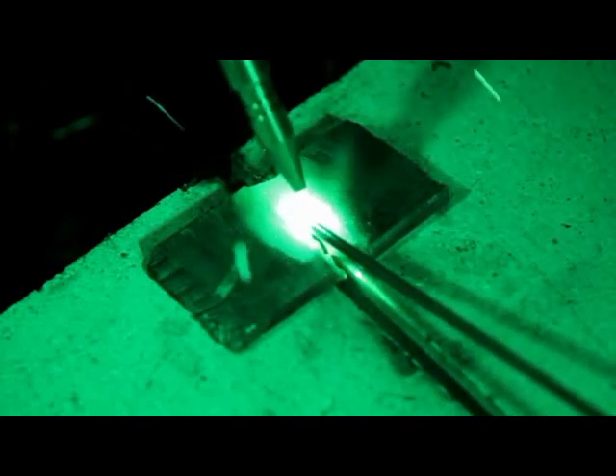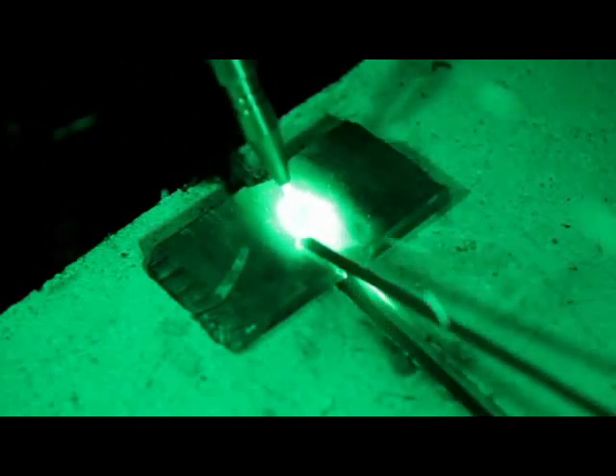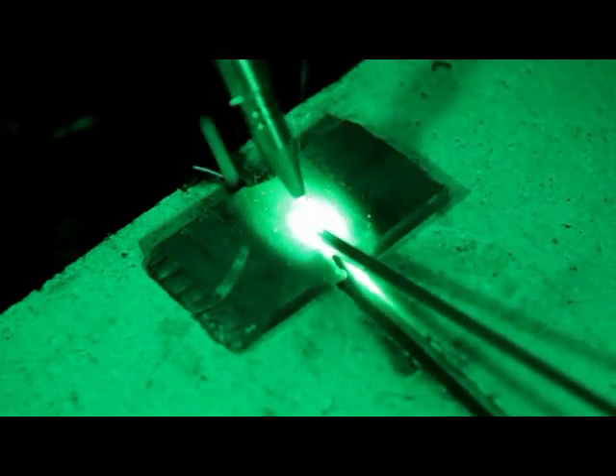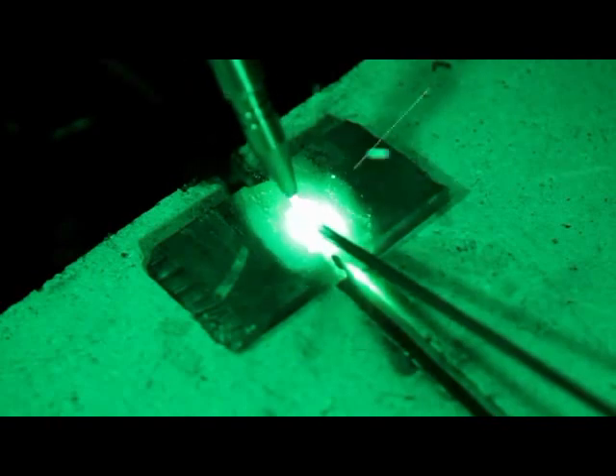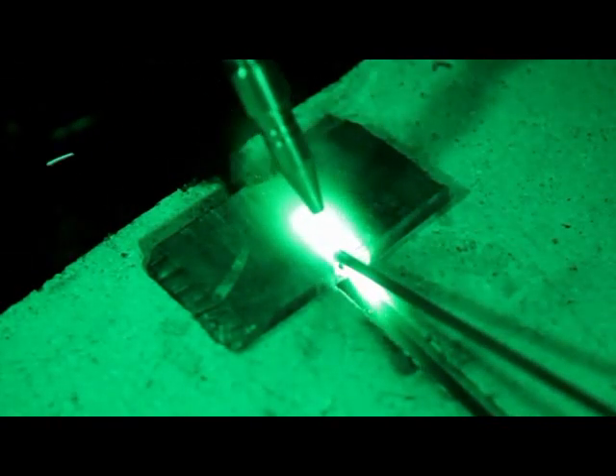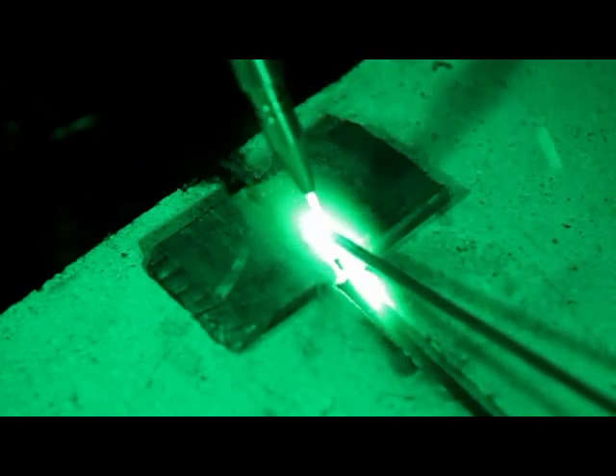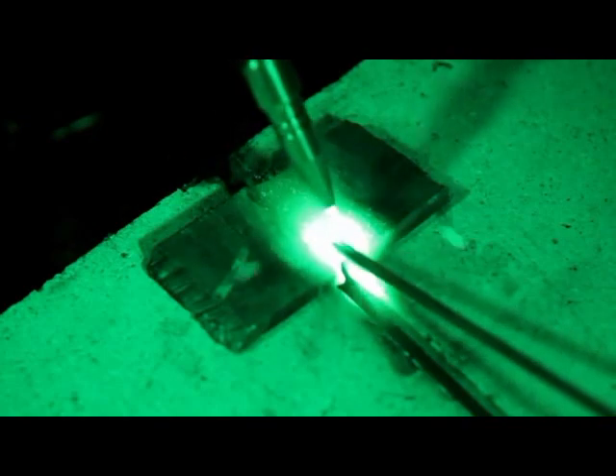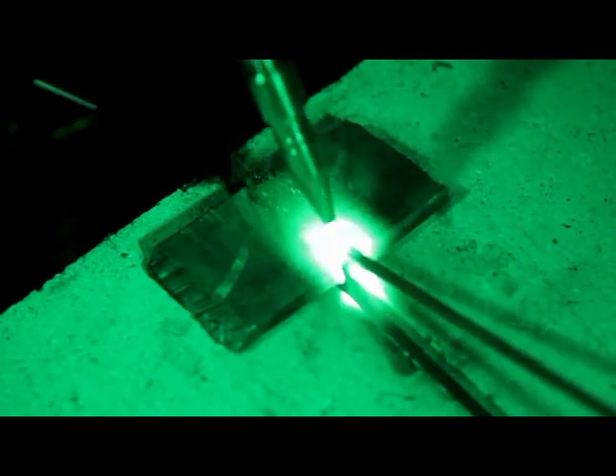Watch that puddle floating to the bottom. You can see it sink down. Come back, add a little bit more rod to fill it up, give you the proper height that you want. A little bit more rod, a little circular motion. Let it heat, sink to the bottom. Come back, fill it up. Let it sink in. You're going to go a whole lot slower. If it looks like it's melting too fast, cut the heat down a little bit. Make that cone a little smaller, or if it's not melting, make it a little bit longer. We're about perfect right here.